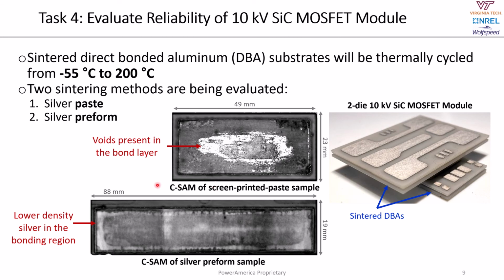In addition to looking at the electrostatic and electrical performance of this unique 10 kV power module, we're also interested in evaluating its reliability. In particular, a unique feature of this power module is the stacked DBA substrates that are used for the top and bottom substrate of the power module. This stacked substrate is done in order to relieve the electric field at the critical triple point that exists between the ceramic, the metal, and the external encapsulation. When evaluating the reliability, we wanted to focus on the reliability of the large area sintering technique that is needed to bond these two DBA substrates together.